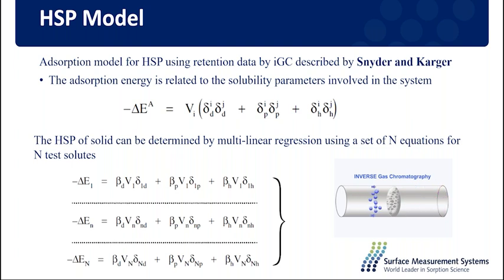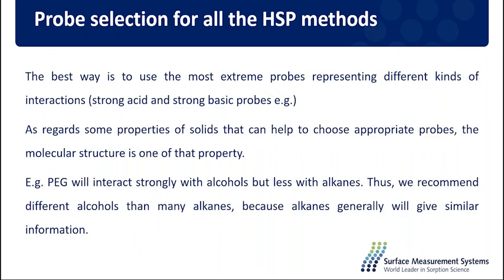You have to inject a series of different solvents, and the software creates this matrix and determines the components of the solubility parameter of your solid using the injected solvent retention data, adsorption energy, which is measured, and the solubility parameters of those solvents. To select the best solvents for the analysis is probably the most difficult part of the measurement, because there's no standard solvent set for every solid. But if you use the extreme probes like strong acid, strong basic, and the typical alkanes, you are fine. But for example, for PEG